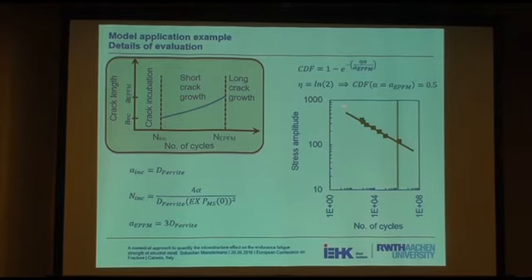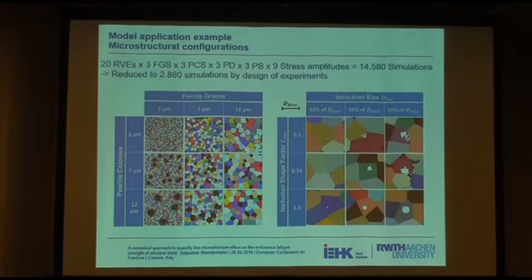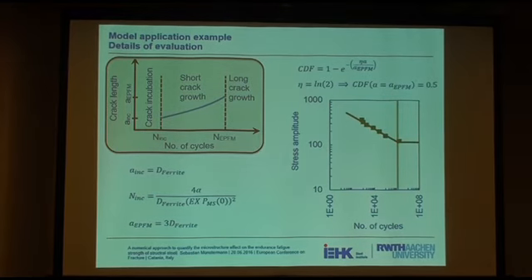And then we could apply different stress levels and express the influence of stress amplitude on the number of cycles at the end of the short crack period. And also we know that roughly at 5 million cycles there will be barriers that become active. So here we cannot trust our simulation result anymore, and we should really run into the endurance fatigue strength.